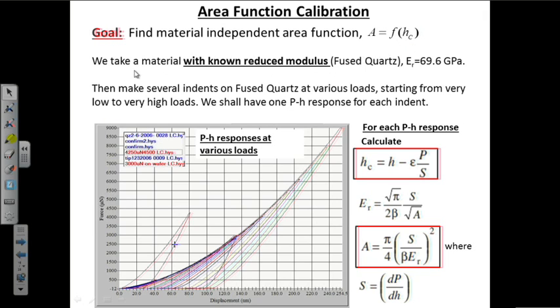So, what we do, we take a material with known reduced modulus. We generally use a fused quartz, which has a reduced modulus of 69.6 GPa, and we make several indents on the fused quartz at various loads, starting from very low to very high loads. For example, in this figure you can see many P-h graphs, and each P-h graph is constructed at a fixed load. So, we have one P-h graph for each indent.